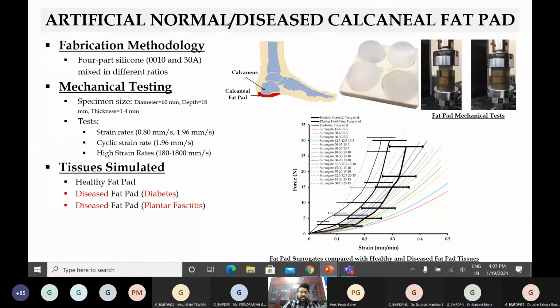We also looked at cyclic strain rates. So what happens when you keep on loading and unloading, because that is usually what happens on the foot. It's not like I walk once in my life and sit down, that never happens. I keep on walking, and this fat pad goes through a cycle of loading and unloading. We also looked at some very high strain rates like 180 to 1800 millimeters per second, which is when you are jumping or going through a lot of impact, like very fast running. So we did this range of tests, and we simulated using our new compositions, 3 different compositions.